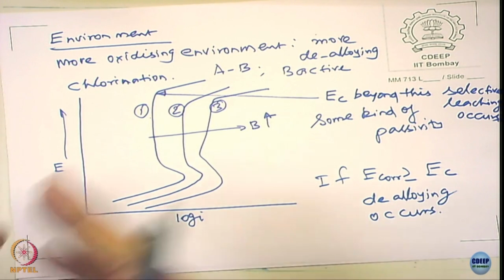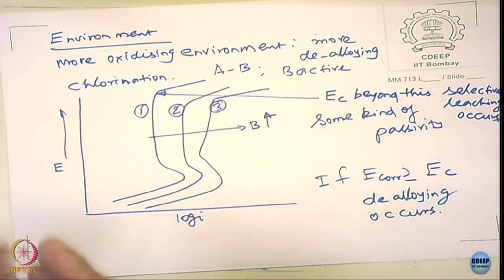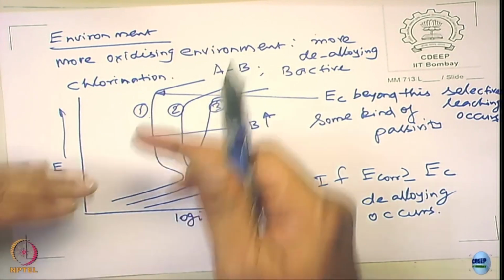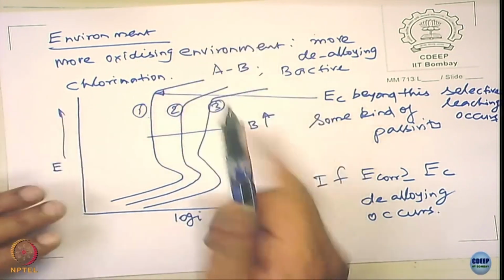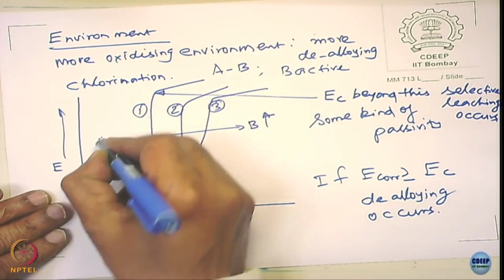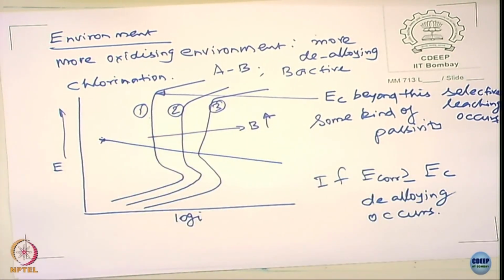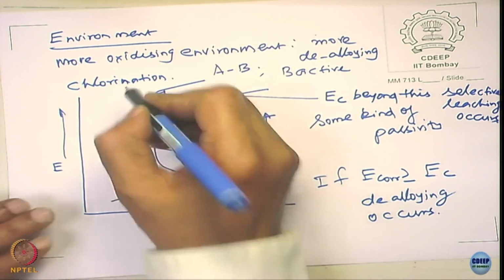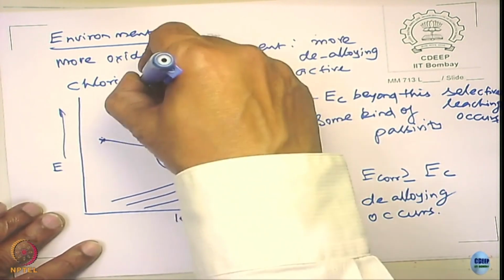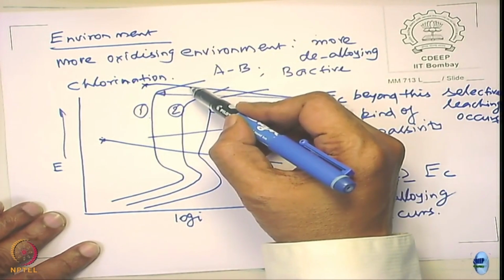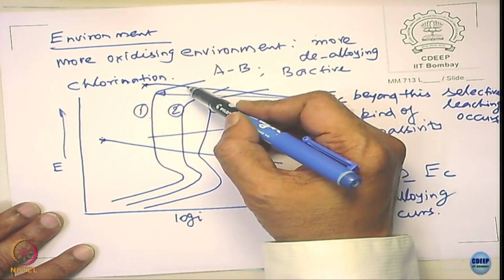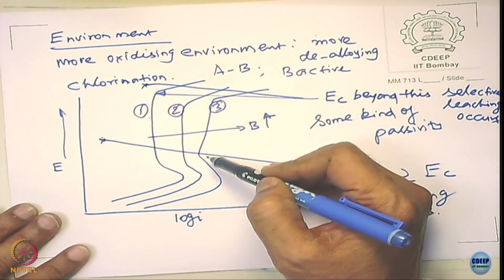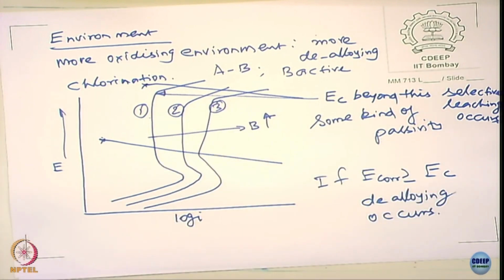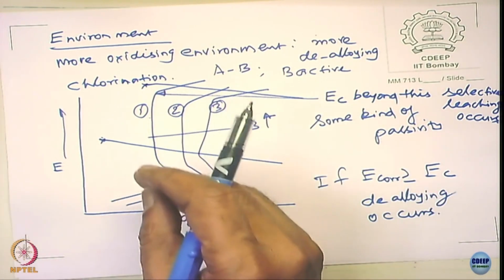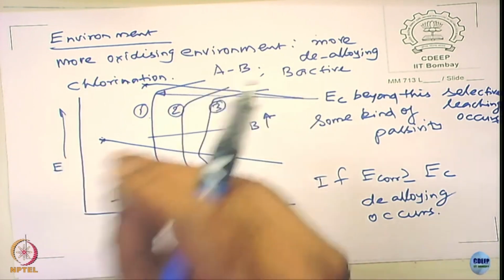So it depends upon the reducing reaction, right? You have one more reaction. This is your anodic reaction. You have a cathodic reaction. If the kinetics support that, suppose this is for the cathodic reaction, it cannot happen. But if the cathodic reaction occurs somewhere here, what happens? The Ecorr is going to lie above the EC, so you are going to have dealloying here, no dealloying here. So what I mean is the environment also is important. If the environment is less oxidizing, then the dealloying will not take place at all.